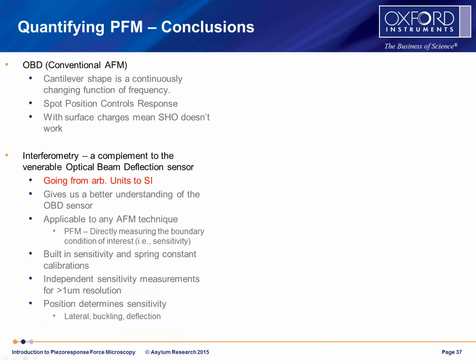Okay, to wrap up this section of the talk on quantifying PFM, we ran into some issues with the optical beam detector in the case of the PPLN, and the spectrograms clearly showed that the cantilever shape is playing a big role in our measured response. It changes continuously as a function of frequency, and also the spot position where you put that optical beam, the laser spot on the cantilever, controls the response.